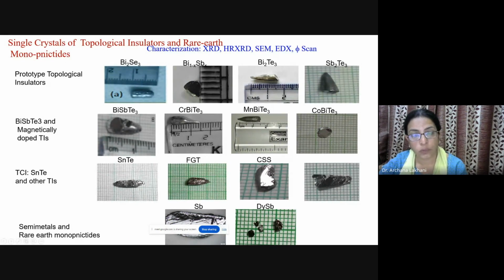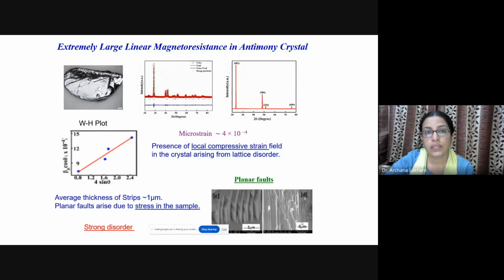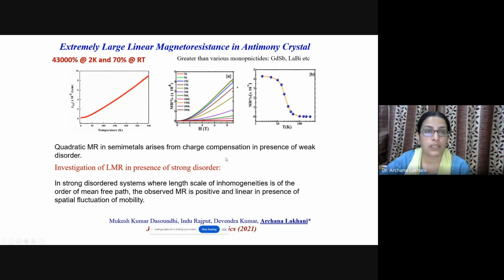These are topological crystalline insulators, SnTe, and some 2D magnetic materials, iron germanium tellurides, and some semi-metals and rare earth monopnictides, which show extremely large magnetoresistance. We have observed extremely large magnetoresistance of the order of 10 to the power 4, 43,000 percent, in this particular single crystal, which is an antimony crystal. It had some specific kind of defects, and the strong disorder generated this high magnetoresistance in this material.